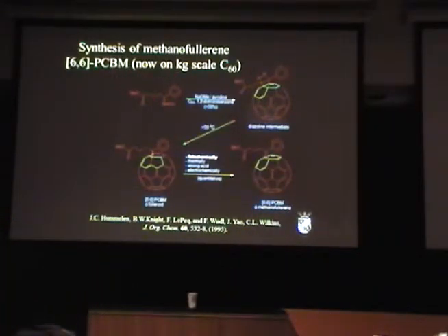Okay, so this is a synthesis of PCBM. You take what this side group has to be, but it has a very reactive piece, a tosyl hydrazone. This is not reactive yet. But then we put some base and we make a diazo compound, which is very reactive. We blow off everything except the 2 nitrogens. And that reacts with this double bond of C60, and it gives you this 5-membered ring. It's difficult to see if you don't know it. It's a 5-membered ring with those 2 nitrogens in that ring. And on this one carbon is this butyric acid and this phenyl group.